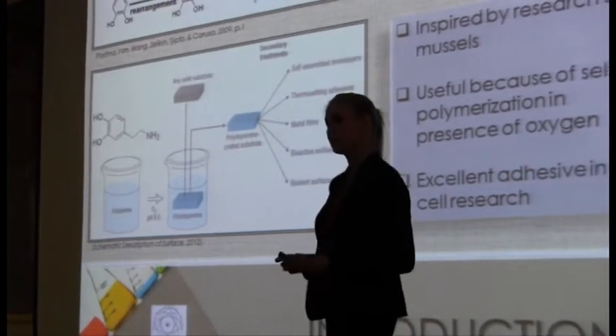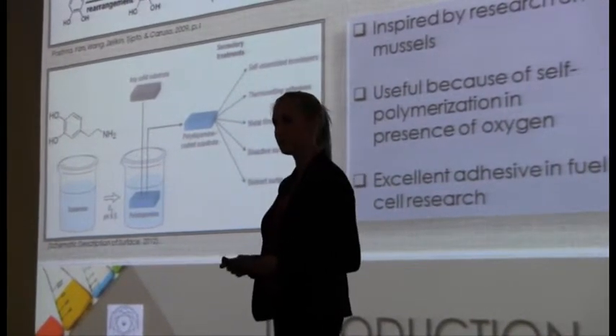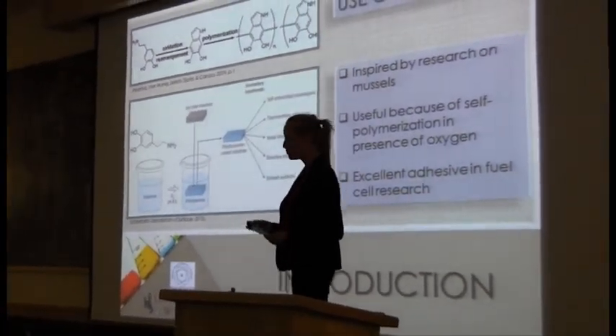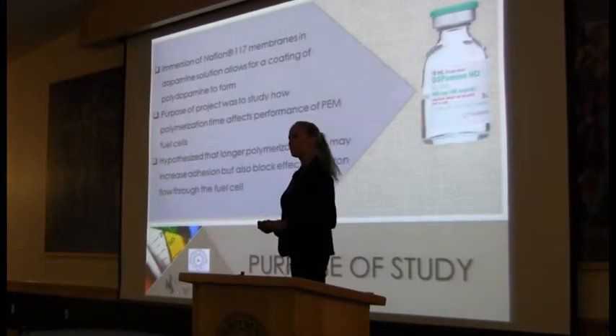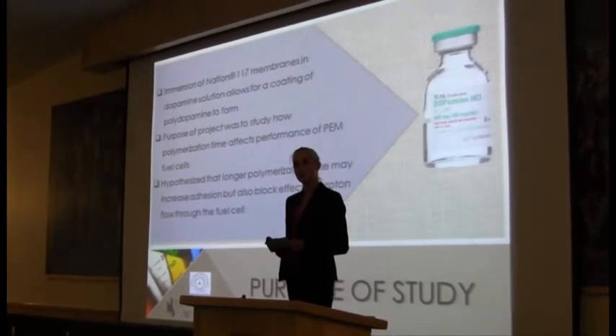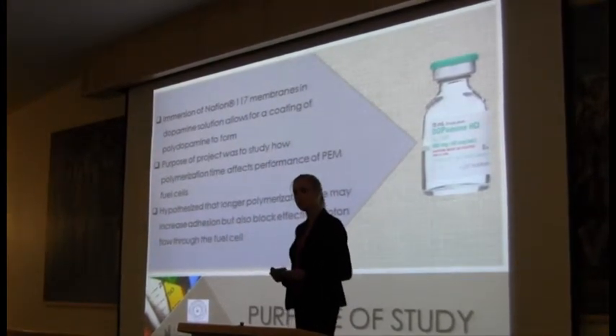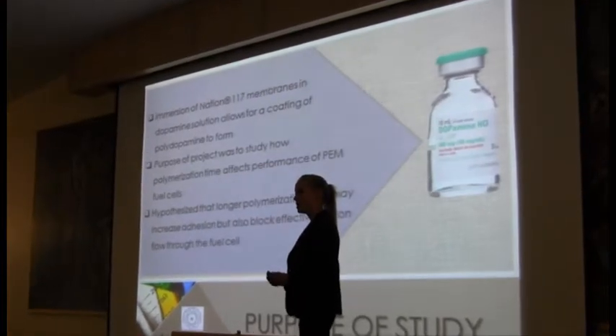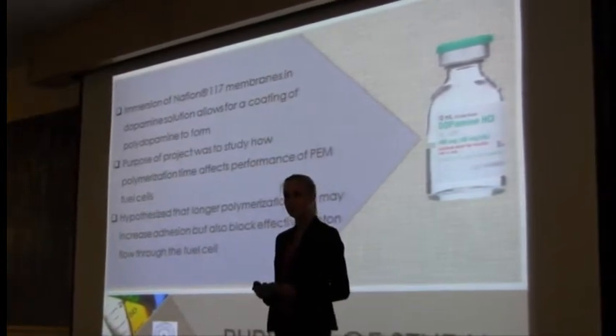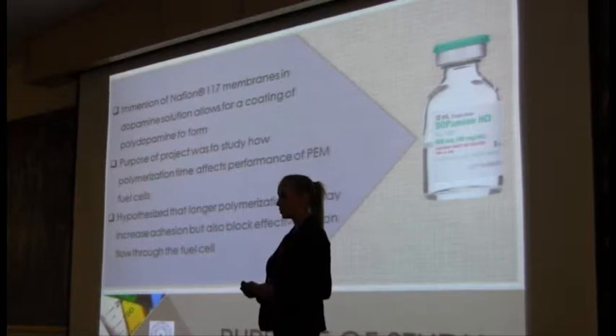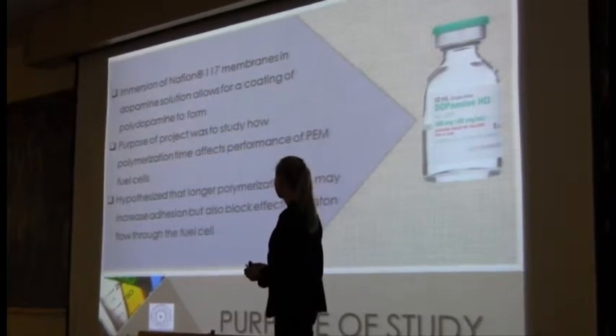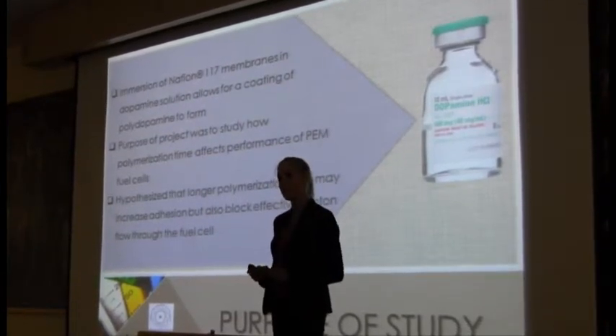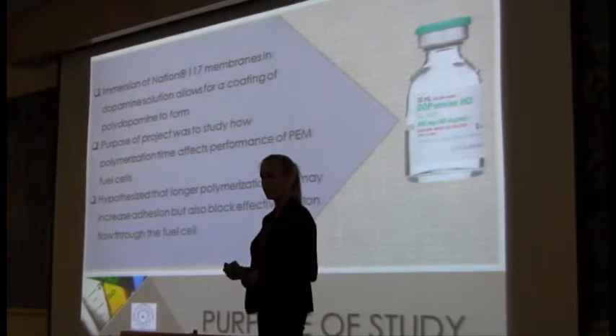From this diagram, you can see that there are a lot of applications that this can be used for. And in fuel cell research, we use it to help the electrodes adhere more firmly to the membrane. So in this experiment, we created 2 fuel cells with 2 different Nafion-117 membranes. We immersed one membrane in an aqueous dopamine solution for 10 minutes, and the other membrane was immersed for 2 hours. We wanted to find out how the amount of polymerization time, or the amount of time that the membrane was immersed, affected the performance of the fuel cell.